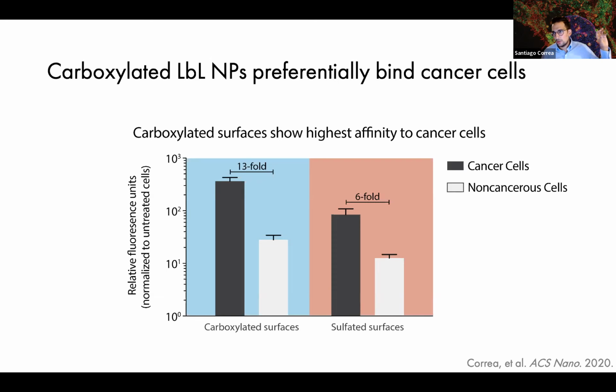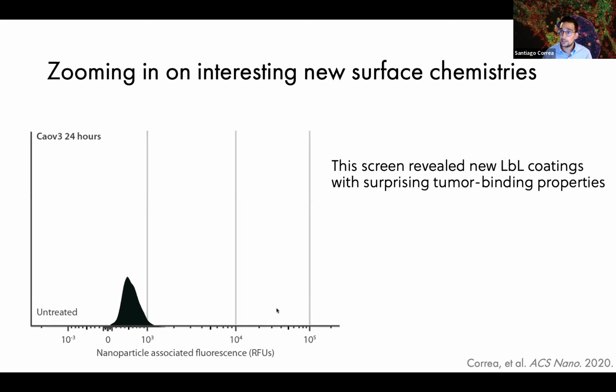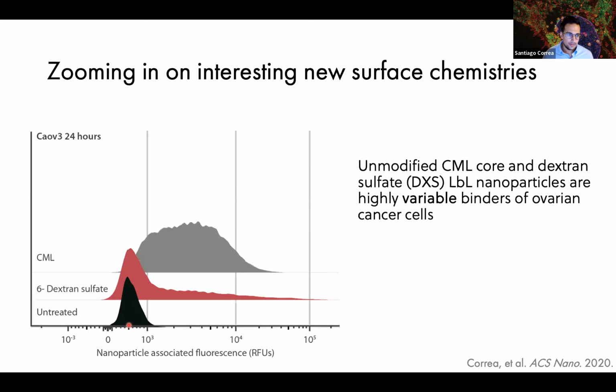If this is a very high level consideration, let's step all the way down into a very granular consideration. Here I'm showing you the raw flow cytometry data for one of our cell lines, Caov3, and this is 24 hours after treatment. Here in black, we have our ovarian cancer cells that have not been treated with anything. This is essentially our background fluorescence, autofluorescence from the cells. Next, let's take a look at cells that have been treated with an LBL nanoparticle coated with dextran sulfate. We see this tail emerge here in the red data. This tail represents our cells that are bound to some of these nanoparticles.